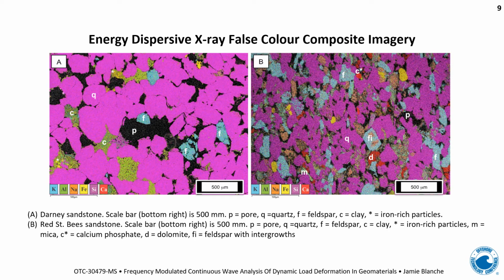So in the previous slide, I discussed the grain-grain relationship and how deformation affects that. Well, the logical next step is to try to characterize the samples that have been loaded, and to do so, we've analyzed them using energy dispersive X-ray via scanning electron microscopy. So it gives us an ability to understand the compositional nature of the samples. And the EDX method allows us to understand the relative proportion of quartz versus clays and feldspars and the presence of other metals within that sample, which you can see in the bottom left of each of these images as the elemental makeup of each of these samples.